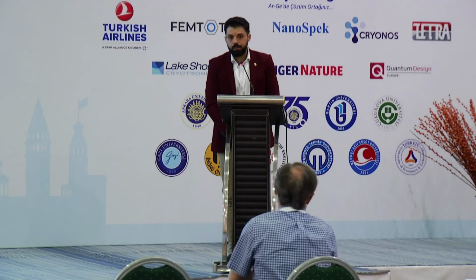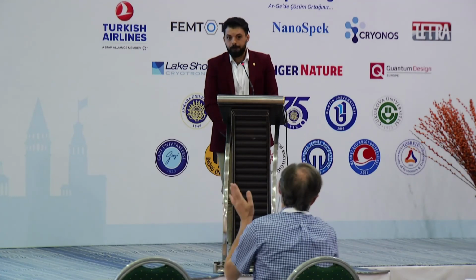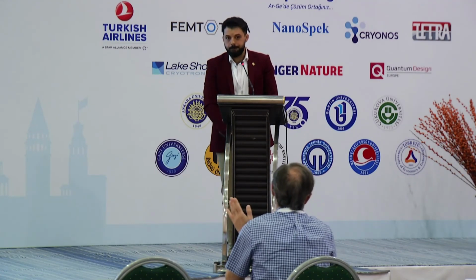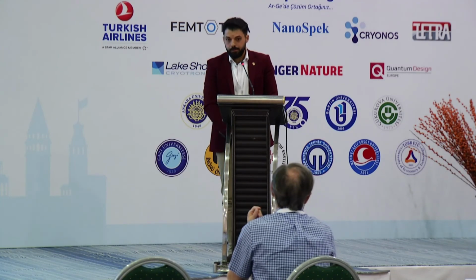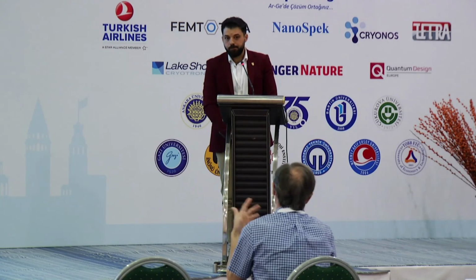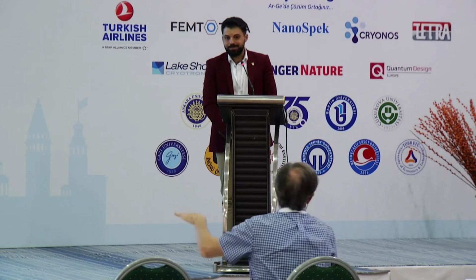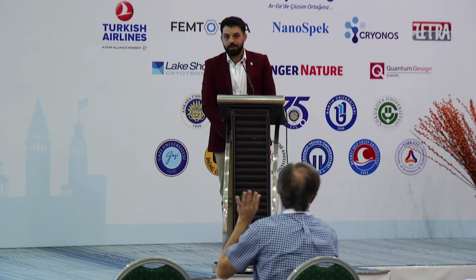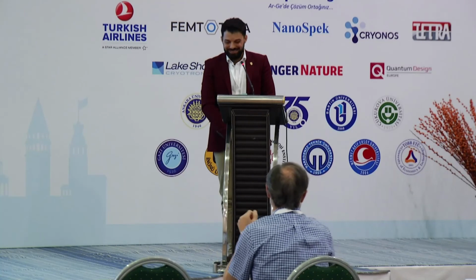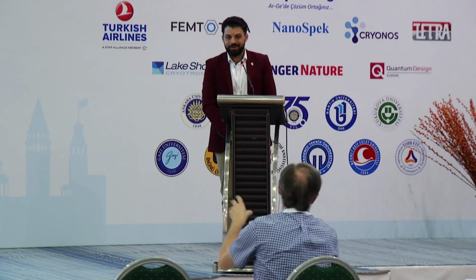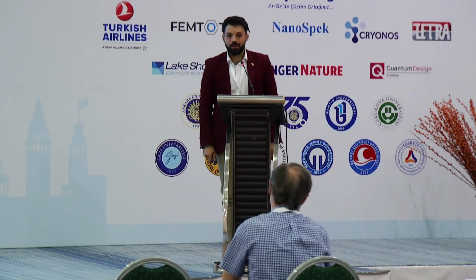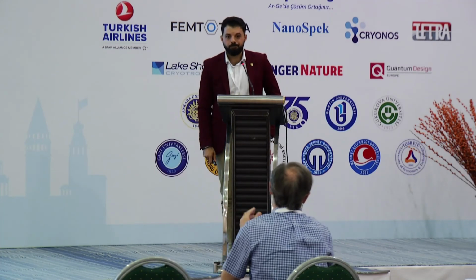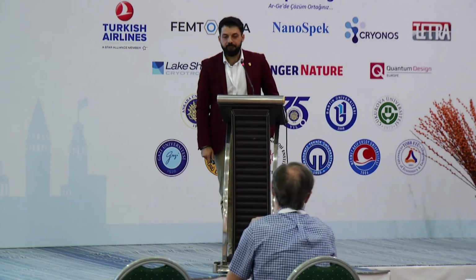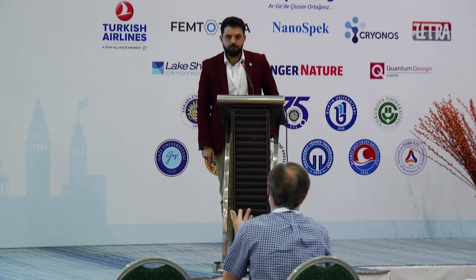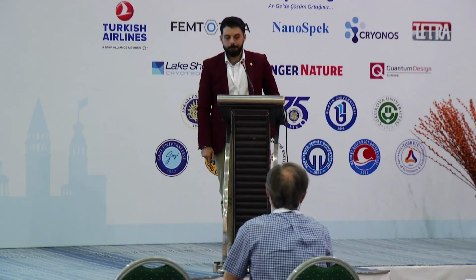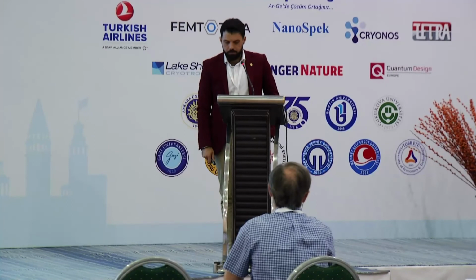You have CO2 again, and even when we work in high vacuum and we measure without taking the sample out into the air, and we have done work with alloys and metals, we still see carbon contaminants even without coming into the air, just from the walls of the vacuum equipment. So we usually do this just to make sure that it's not contaminants that have adhered, and this is what we measure. But I guess when you have nano materials dispersed, it's quite difficult to do that.